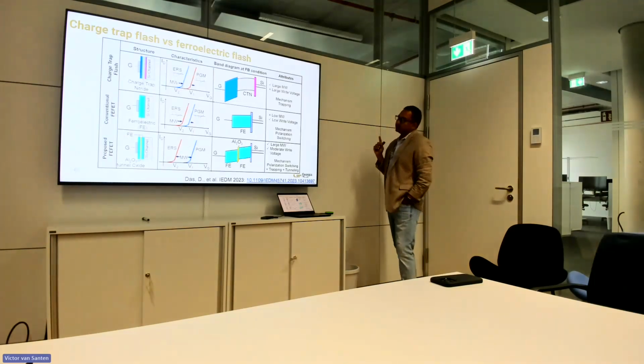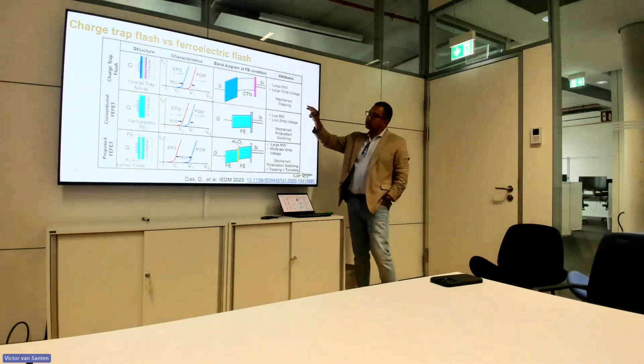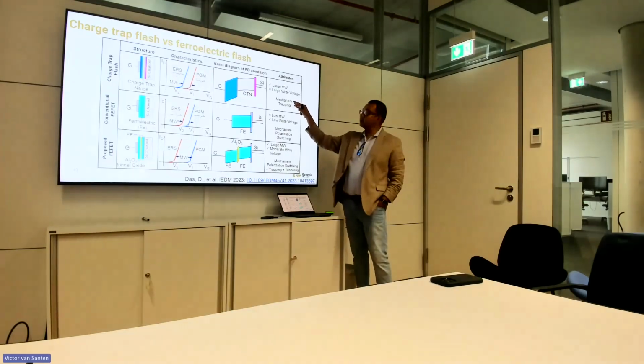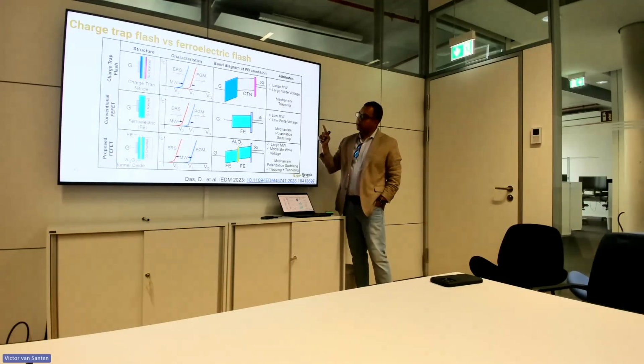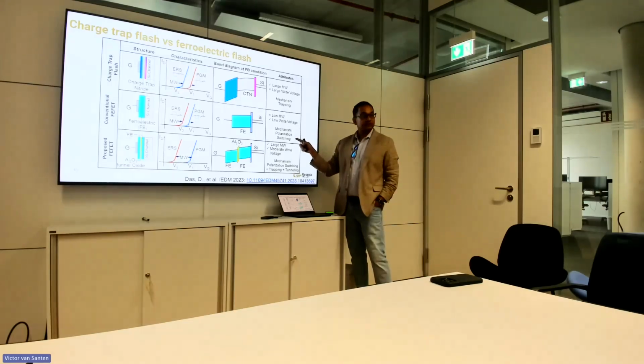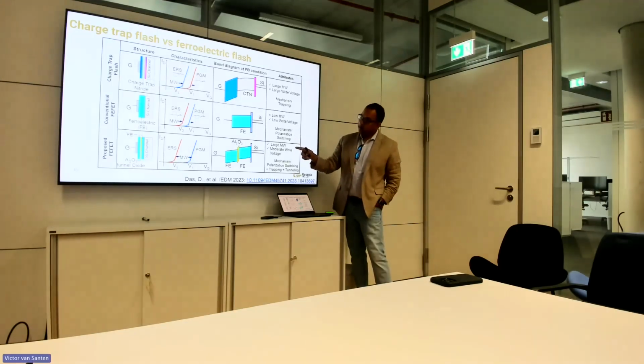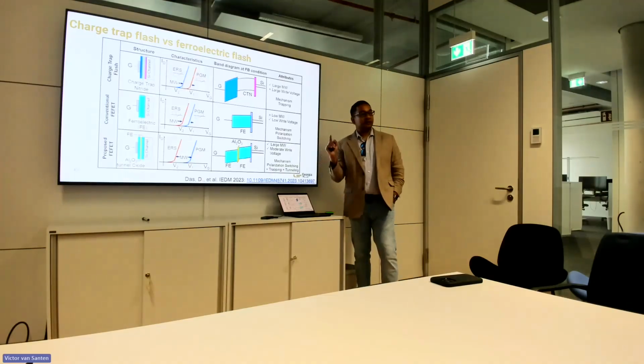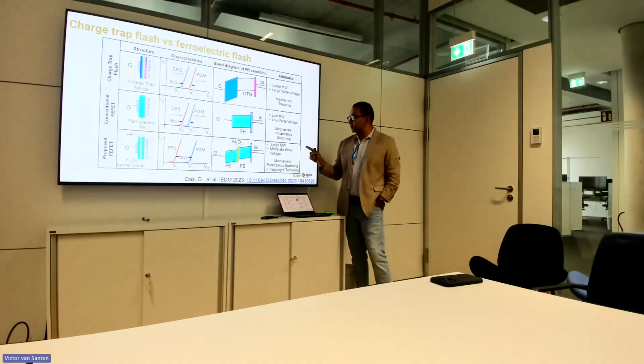So I'll quickly go over the comparison. First, traditional NAND flash has a large memory window, but it comes at the expense of a large write voltage, and the mechanism is trapping. In the case of a conventional ferroelectric field effect transistor, the good thing is a low write voltage, but the memory window is also low, and the memory window mechanism is polarization switching. Now, in our case, we are putting an aluminum oxide layer, or a dielectric layer, in the middle. We get a moderate write voltage, but a large memory window.